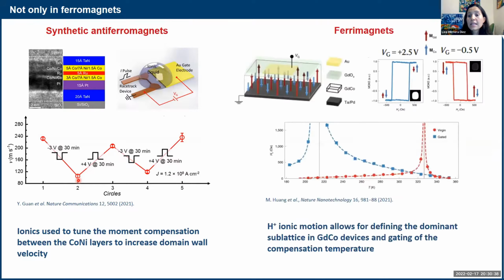And then, of course, this was seen as well in natural ferrimagnets. In natural ferrimagnets, you also have two lattices that are competing with the alignment of the magnetic moment. The two lattices are aligned anti-parallel to each other. So these are not two layers like this one coupled by a ruthenium layer in between. These are really two lattices. It's one material, gadolinium cobalt, and they could see that by using magnetoionics, once again with proton motion, they could define which one of the lattices was the dominant. They could switch between gadolinium dominated and cobalt dominated, as you can see here on the top. And you can see nicely that the Kerr signal from the cobalt really flips sign as they do this.